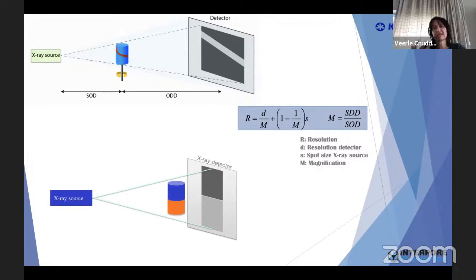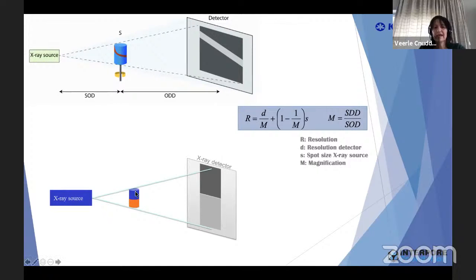So you're intrinsically influencing the resolution. If you have a small sample, you can put it closer to your X-ray source, giving better magnification and allowing you to see more. That's immediately why, when people work with micro CT, the samples are most of the time rather small, or we try to find a balance between what is still okay in sample size and what is needed to see the processes. That's an important aspect of micro CT.